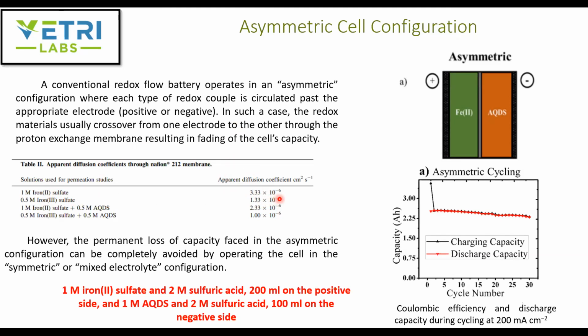Since the diffusion coefficient that they have measured across the Nafion 212 membrane is closer to the aqueous solution, there is a high chance that iron is going to crossover, like diffuse through the membrane and reach the other side. So you're going to have capacity fading. And that is what they noticed.